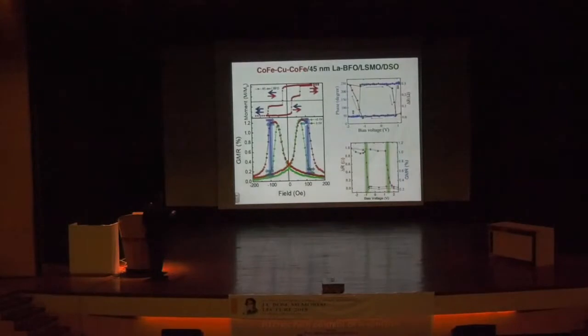But what you can see is with 2.5 volts, it shifts significantly between the red and the green, telling you that I have now changed the magnetization direction with just 2.5 volts. So we've gone from 8 volts, 5 volts, now to 2.5 volts. And the switching actually happens around 1 volt. Okay? And you can see all of that summarized here. The phase of the piezoelectric switching and the resistance are all matching up around 1 volt.